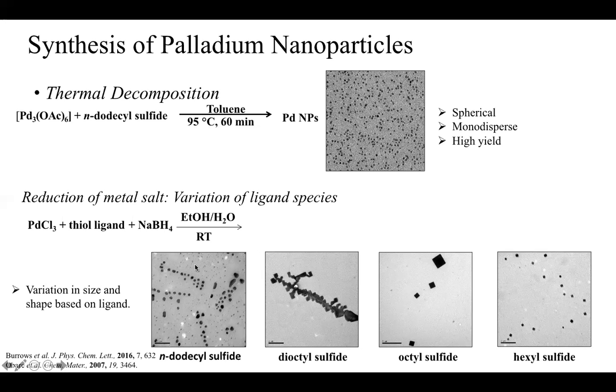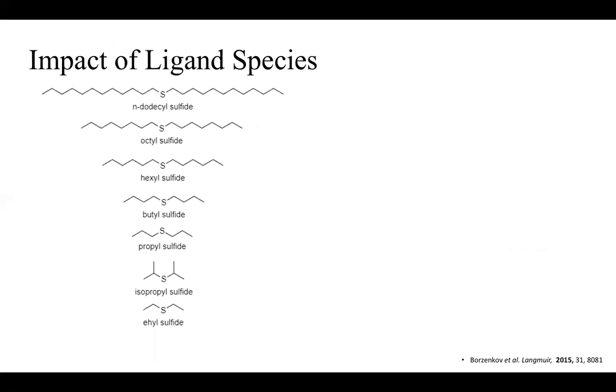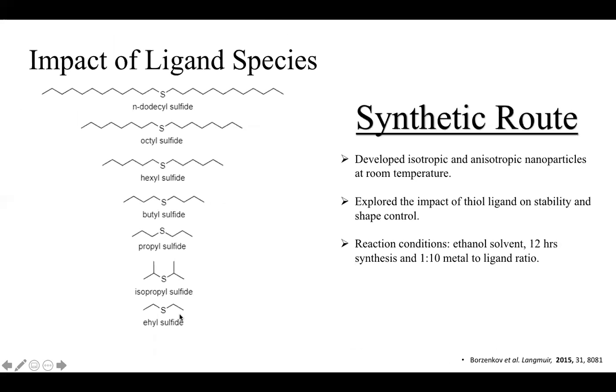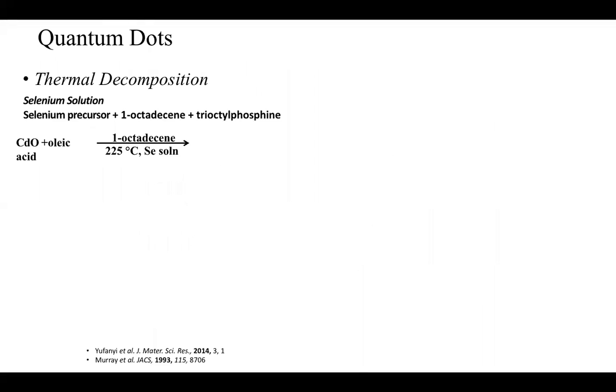But we were able to get various shapes based on that ligand species. So we were able to tell the impact of our ligands play a direct role on the synthesis of these methods and how they grow, which also shows that if we're making nanoparticles with different pathways and growth, they have different surface properties of how they interact. So again, we were able to develop isotropic and anisotropic nanoparticles at room temperature that explored the stability and shape control based on that thiol ligand over time.